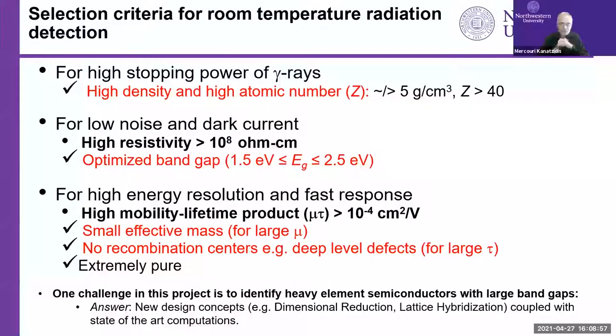So what materials are likely to be good? Here's some of the criteria, not all of them. We need something that has heavy atoms, that has high density, so that it can absorb the gamma rays. We need dark current to be low, as I mentioned. So we need high resistivities, which are at least 10 to the 8, ideally much, much higher. The band gap should be 1.5 eV or higher. Otherwise, you have too high of a dark current at room temperature.